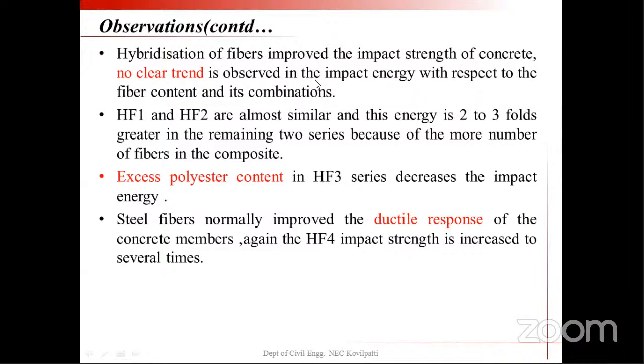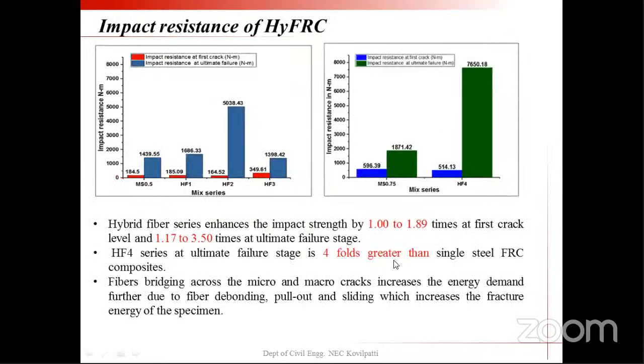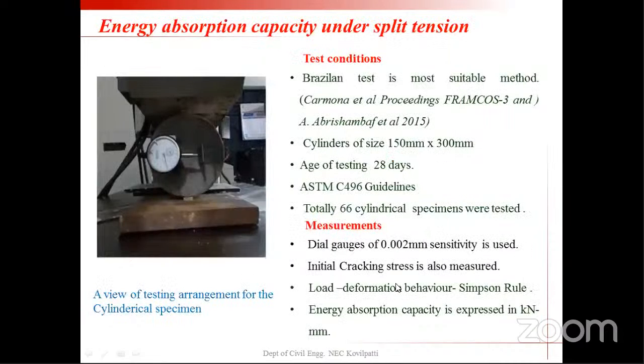With these values, I am not able to conclude because the values are changing very randomly. So it is very difficult to make a clear conclusion on impact resistance in hybrid FRC with respect to the fiber content. And excess polyester fiber content decreases the impact resistance. And the highest energy observed in the HF4 series shows the ductile response of the members. Impact resistance has been increased several times. The same comparison has been made with the graph. And next, the energy absorption, toughening and toughness characterization has been measured under split tension.